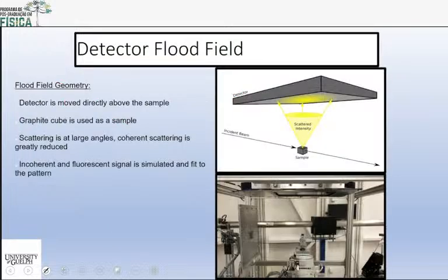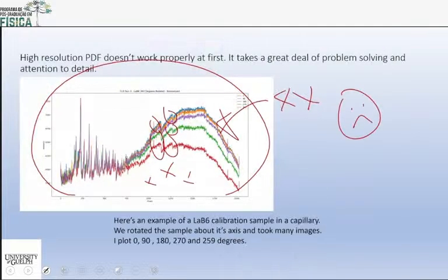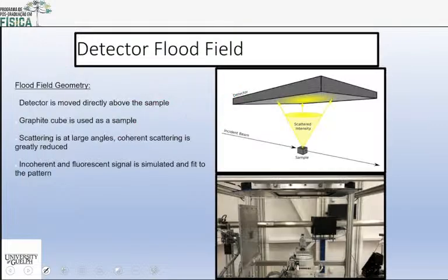What we realized was that the detector was part of the problem. Well, one, the sample was part of the problem. It was sort of shaking around, and I call it the washing machine effect. It's all sort of moving around. And as we rotate the tube, the sample, sometimes we had more sample in the beam, sometimes we had less. With that, we had to stop that. We had to tighten up the sample better. That was good. But the glitches were more serious and harder to solve.